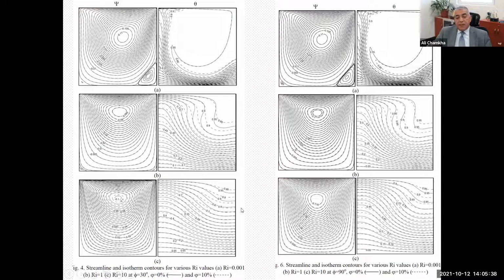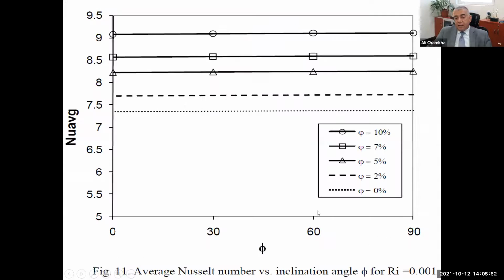These are typical streamlines and isotherms. This is a mixed convection, so you will have a critical number which is called the Richardson number, which I used here. For small Richardson number, you have conduction cases, and then you'll have higher cases for Richardson number. This is for Ri=0.001, and I have other cases. These are conduction cases. You will see this is the inclination angle of the cavity. You will see that in principle, as you increase the volume fraction, you will have an increase of Nusselt number.